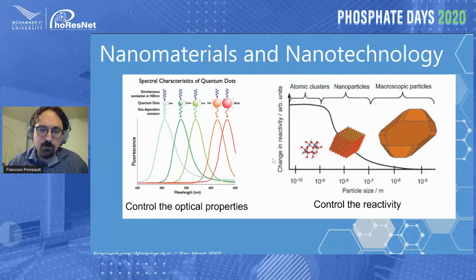On the right, you have another very classical example in terms of surface reactivity or catalytic property. Here you see the effect of size on the reactivity per unit of particle. And you can see that there's a clear increase in reactivity as you decrease the particle size. And if you recall that 1 to 100 nanometer threshold that we were discussing a bit earlier, well, this is your 1 to 100 nanometer range here on this graph.